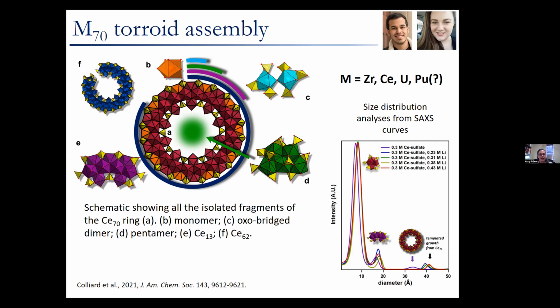We can see using SAXS that these monomers can bridge to form a dimer and then grow to form larger species. So in the crystal form, the M70 toroid also has this pentamer, or five metal centers, in the middle of the toroid. And then larger parts of the ring include Ce13 and cerium-62. The cerium-62 we were able to crystallize separately. And it's really cool because they form these interlocking rings and then can grow into extended structures through the addition of additional countercations.